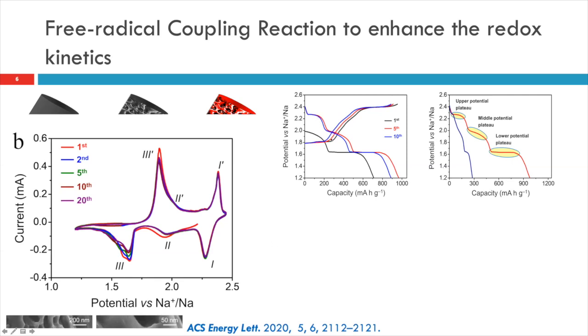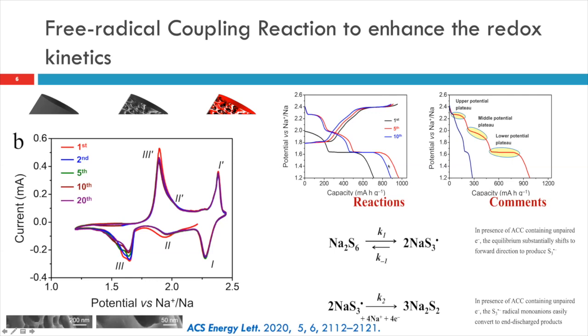it is observed the same way people observe: the first transitions happen from higher polysulfide to lower polysulfide, then goes to the transition to the solid phase formation. But here, what we observe is one middle plateau, and we are interested because this was not very common. At least we have not seen many reports on that, and some people have shown it, but not explained properly. And here also you have seen at 1.85 that the middle plateau is coming, and we tried to understand what this middle plateau is about. So what we came up with, I'll talk about in the next slide.